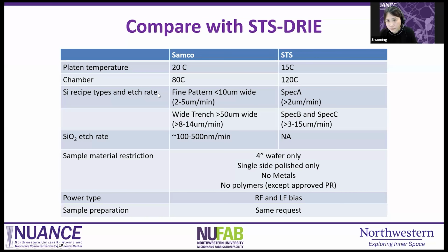Etching performance. For silicon fine pattern, if you want to etch a trench, a hole, whatever the pattern, with opening size less than 10 micrometers, we have a standard recipe called fine pattern in the new SAMCO, and another standard called Spec A in the existing STS. They're equivalent. They both etch about 2 to 5 micrometers per minute or even smaller. On the next page, I'm going to explain why the etching rate is always a range.